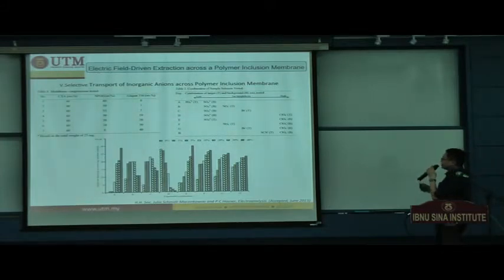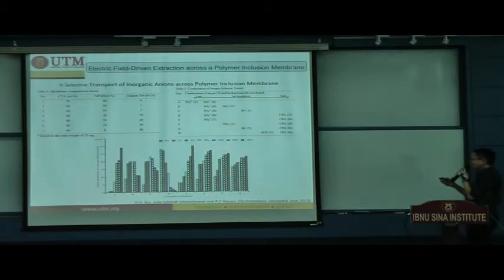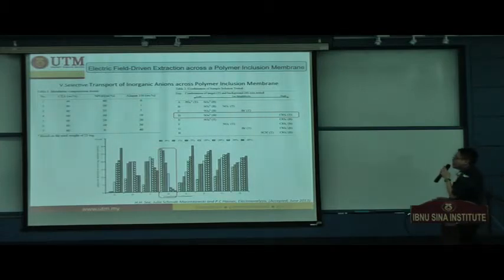So it's not necessary to look at all the results. You just focus on 2. The first one is experiment D. If you want to extract sulfate, which has low lipophilicity, you look at the result of sulfate detected in the receiving solution. Membrane number 1, which contains no Aliquat, resulted in the highest amounts of sulfate detected in the receiving solution. But if you're using a membrane with 40% Aliquat, the sulfate disappeared, which means it still remains in the sample solution or stays inside the membrane and does not go through to the acceptor solution.